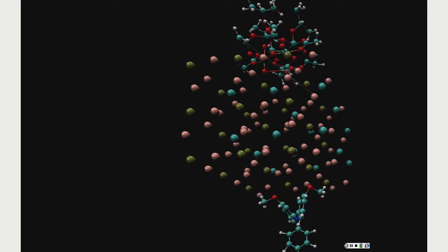You can make tricks, freeze some molecules, heat everything, then heat the guy, and then during molecular dynamics, unfreeze. Let the heat slowly dissipate from the semiconductor to the organics. Or you can freeze everything except the carbons which are really involved in a connection.